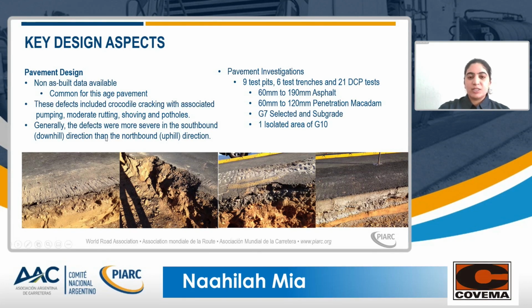The investigations that were done on this road, we had 9 test pits, about 6 test trenches, and 21 DCPs. From the test pits, we gathered the information that the asphalt surfacing right now is between 60 to 190 millimeter thick asphalt. The subbase was 60 millimeters to 120 millimeters penetration macadam, so the largest stones. G7 selected in subgrade, and then 1 isolated area where the subgrade was a G10 material.